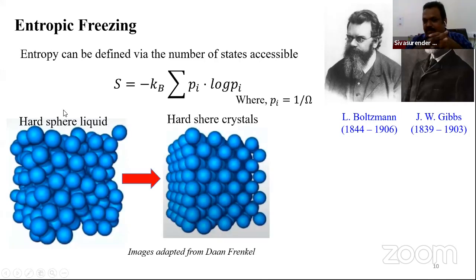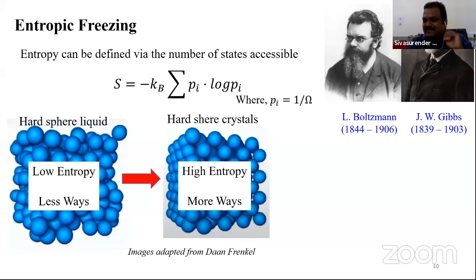So what we could now clearly show, both via calculation and in computer simulations, is that these hard sphere liquids cannot be arranged in as many ways as a hard sphere crystal can be arranged. So there are more ways of forming a hard sphere crystal than of forming a hard sphere liquid. Thus, from a microscopic definition of entropy, we are speaking about a liquid which has lower entropy than the crystal, right? So the definition of degree of disorderness still holds, but we are now speaking about degree of disorderness at the microstate level, in a more microscopic level.